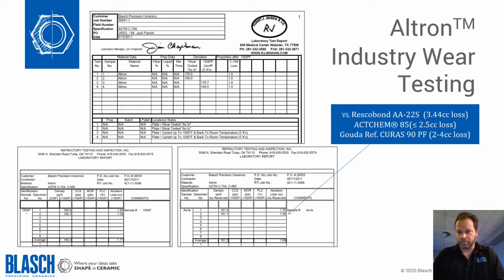Those numbers, as you can see in the upper right, are roughly around 3 to 5, and that's a lab test. Now, in the field where you're installing it and you have to apply moisture and dry it out, cure it out, we suspect that those numbers are actually worse. Where Blasch is Altron, it's fired in a controlled atmosphere, fully dried, fully cured, put in a box and ready to install. We are accurately getting well below 2 cc loss for this material.